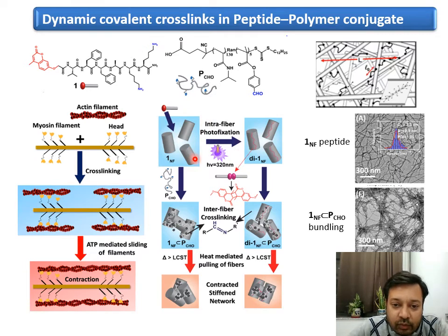So we took this intra-fiber photofixation, and it can form this crosslinked network. If you heat the system up, it can collapse the system and probably give a strain stiffening material. We have also compared that with this photofixated sample, and in the photofixated sample as well, it does the job. When we looked into the microscopy, we did see that the single filaments of the peptides can be bundled together to form this kind of bundled conjugate network.